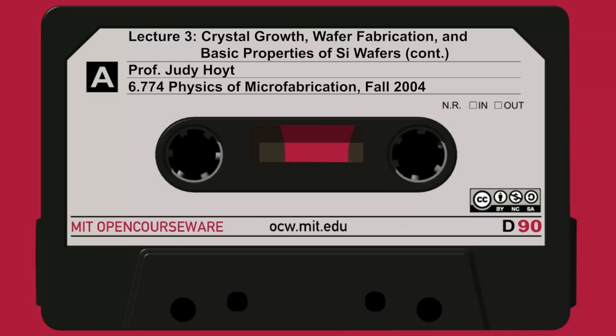So in this case, I've doped it. The Fermi level is here. EF is now above the V minus level. So EF is up here, above the V minus level. So it means this level is occupied with an electron. So it's acting like an acceptor. And in fact, V minus is going to be, in this particular case, for this position of the Fermi level, the dominant vacancy charge state.